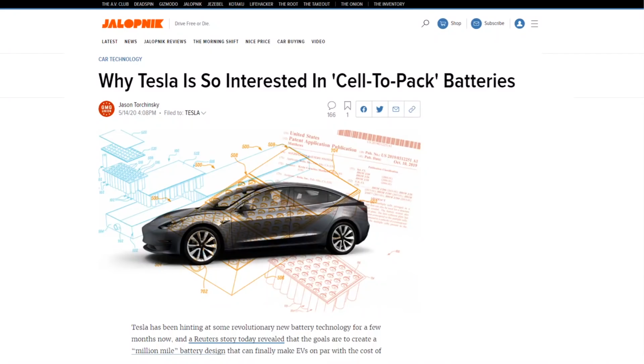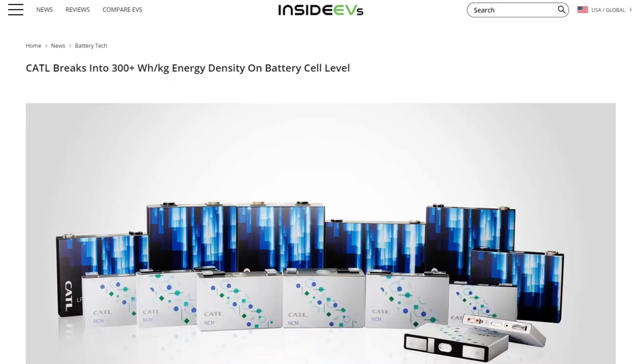the energy density at the pack level, there's quite a loss with NMC. So what LFP has managed to do is go from cell to pack. So the differential in energy density has narrowed, and that's made it more competitive at the pack level versus NMC. NMC at the pack level is still very high. Some of the CATL ones are nudging 300 now, watt-hours per kilo, which is very high. But at the pack level, it's lower.